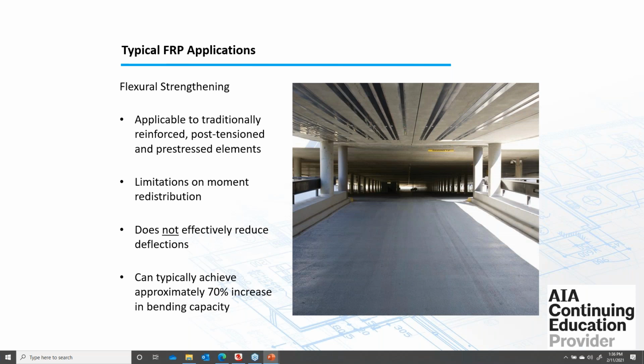Unfortunately, no. If it was deflecting 4 inches before, it's going to probably deflect 3.8 or 3.9 inches. So it really does not affect deflection at all. And the reason for that is it's just not nearly stiff enough to actually reduce deflections. You'd have to do a steel plate or something that's much more stiff than the FRP.